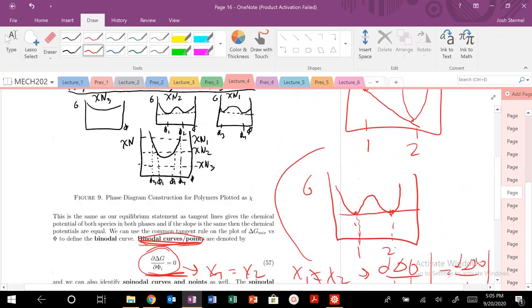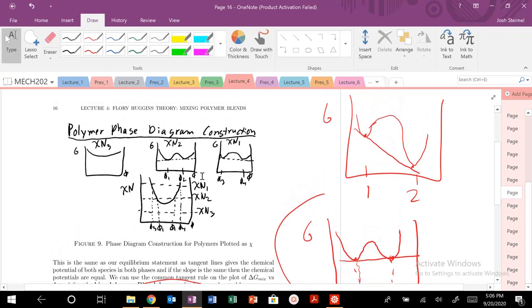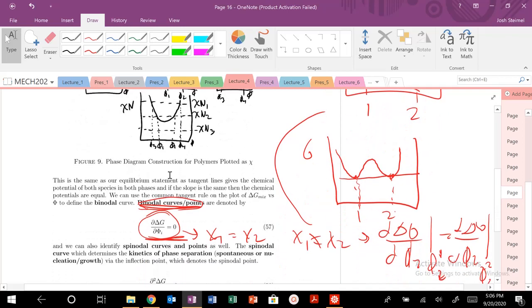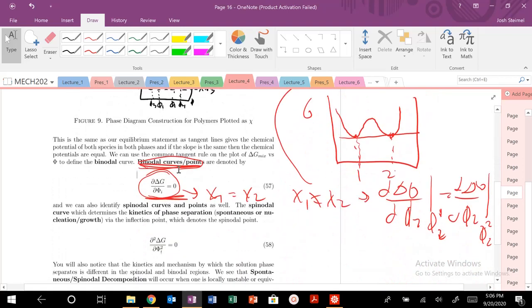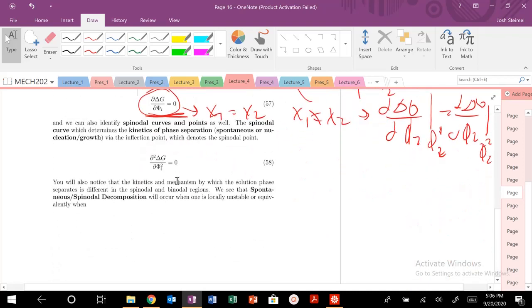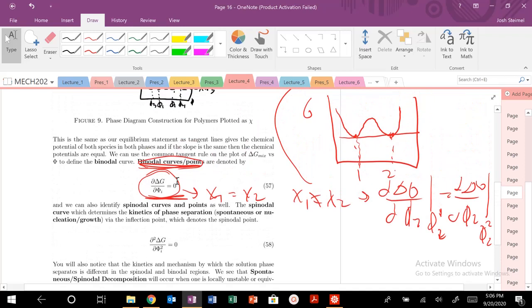Finding the common tangent — and thus the binodal curve — is really impossible unless we have a symmetric system, because for each free energy curve you have to find mathematically where the instantaneous derivatives at all points match. So unless you have a symmetric system, I'm probably not going to ask you to figure out the binodal curve.